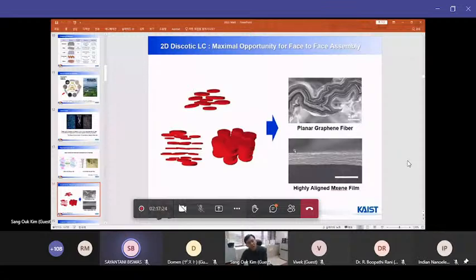Then how about a 2D liquid crystal, like a 2D graphene-like structure? The left side shows schematics of disc-like liquid crystalline phases, like discotic nematic, discotic smectic, or columnar structure. In all those different liquid crystalline structures, the 2D discs are oriented in the same direction, right? So if you use these liquid crystalline states as a precursor for processing, you will get a highly stacked 2D structure in a very easy way.